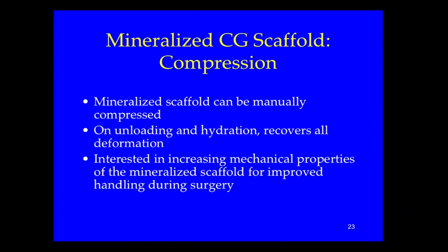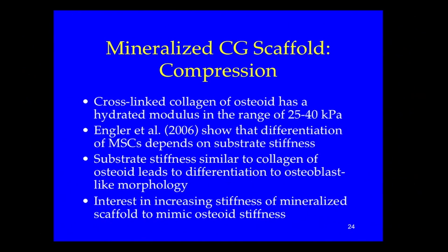One of the things we found was that with these mineralized scaffolds, you could manually compress them. If you pushed them down and you hydrated them, they would recover all the deformation. But we were interested in improving the mechanical properties of the mineralized scaffold for improved handling during surgery. And there's another reason that I'll get to as well.